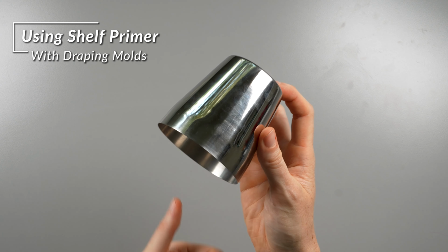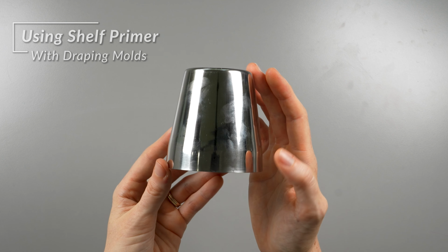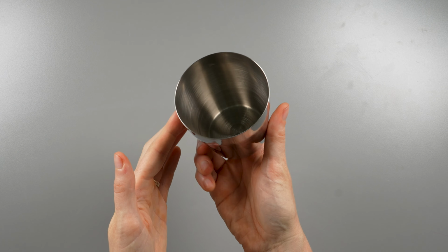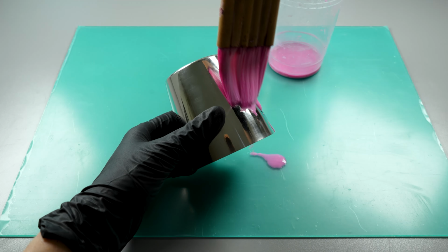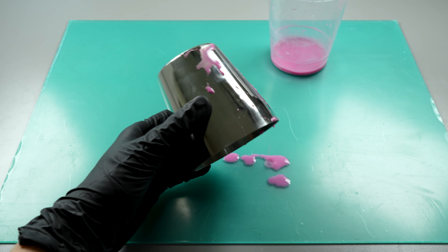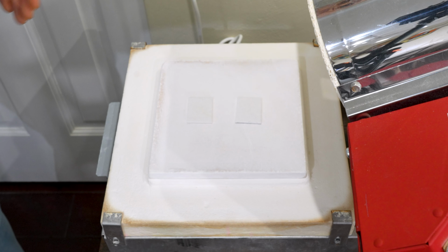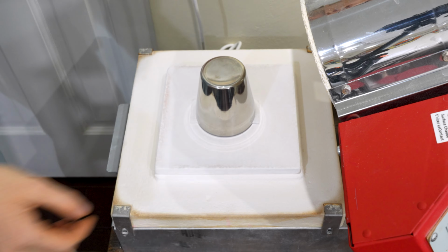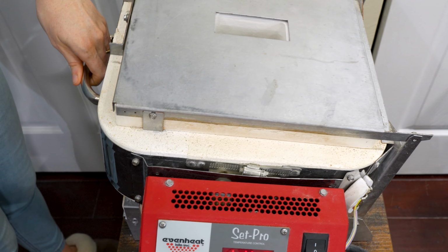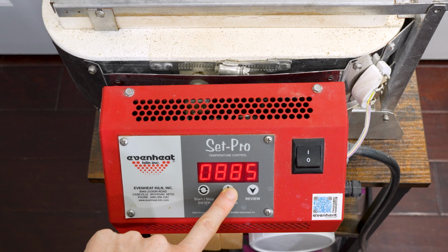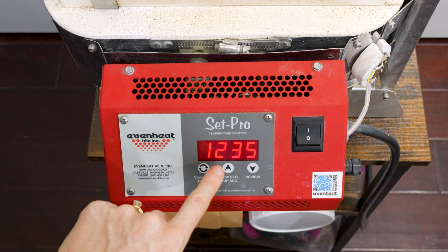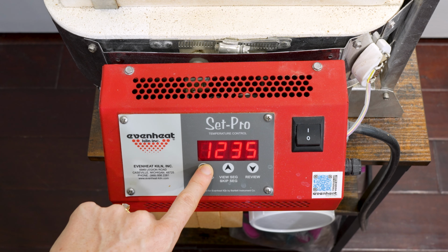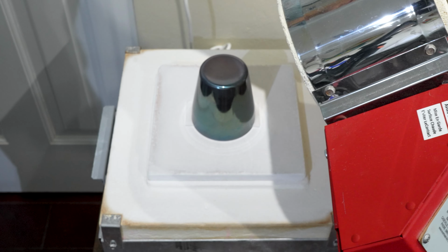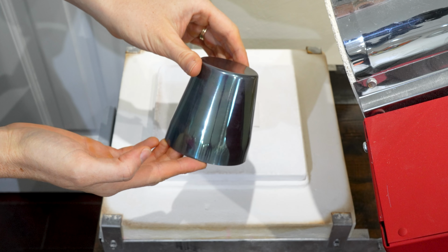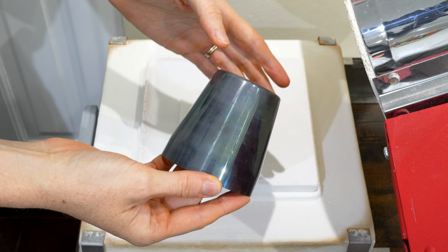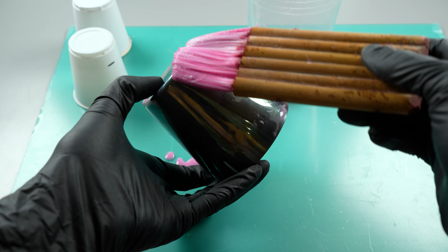Draping molds are typically made of stainless steel instead of ceramic. We'll discuss exactly why that is up next in Lesson 8, but because of this difference in material, shelf primer doesn't adhere to draping molds as readily as slumping molds. To help primer stick, I suggest that before using a draping mold for the first time, you kiln fire it alone up to the process temperature you plan to use it at, which should be somewhere between 1200 and 1300 degrees Fahrenheit. This will not only remove any residual oils that may be left over from the mold's manufacture and cause devitrification, but it will also impart a slight texture to the surface, better allowing the primer to grip on.